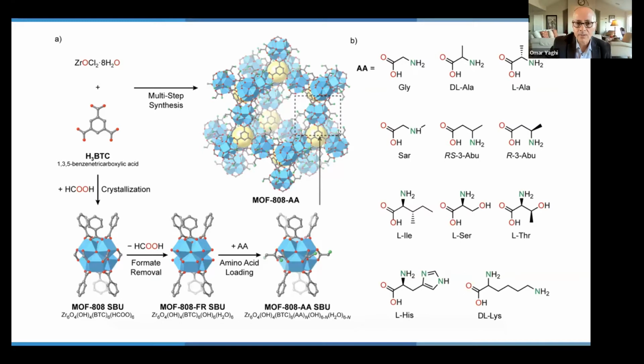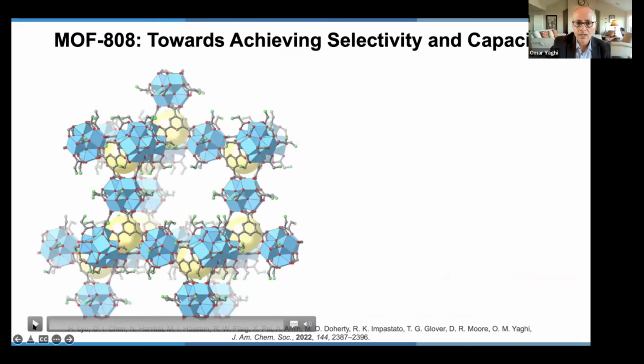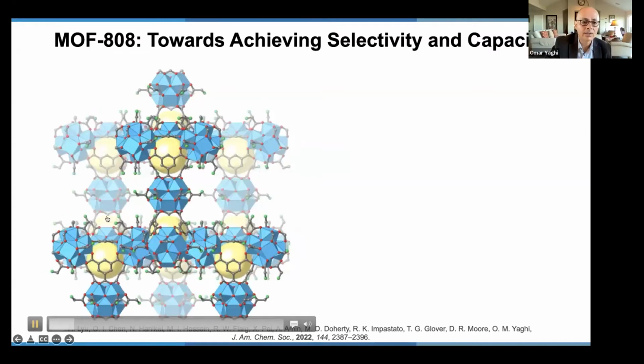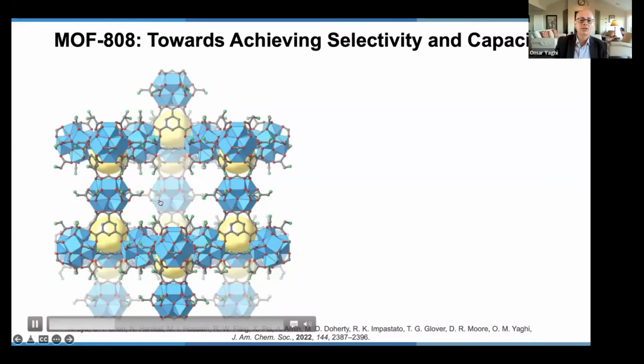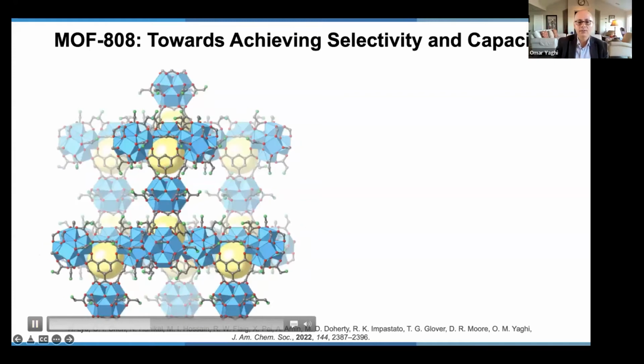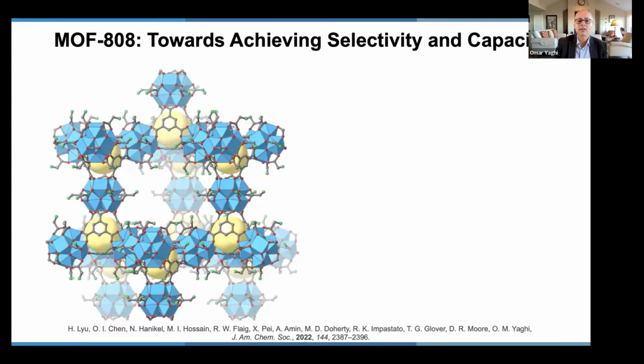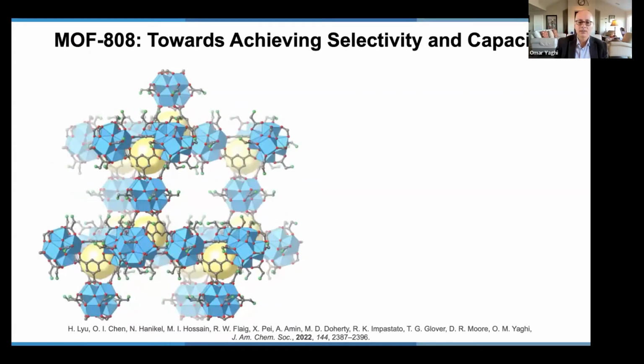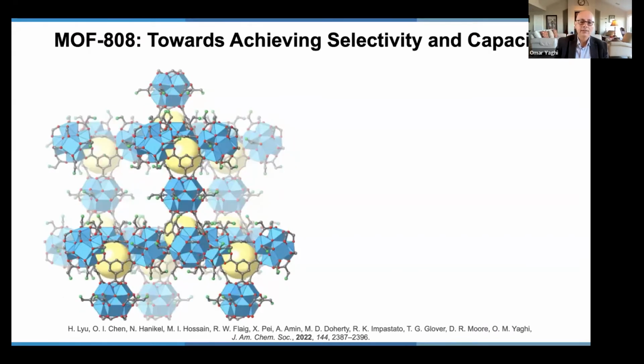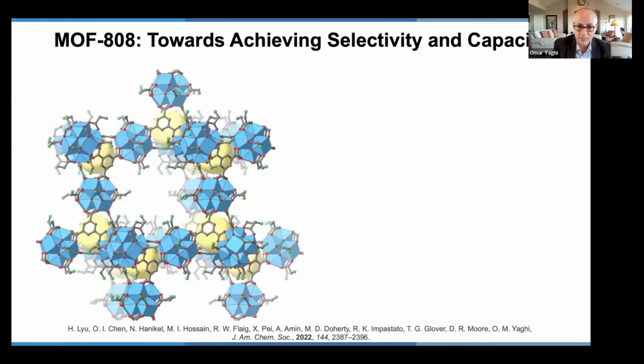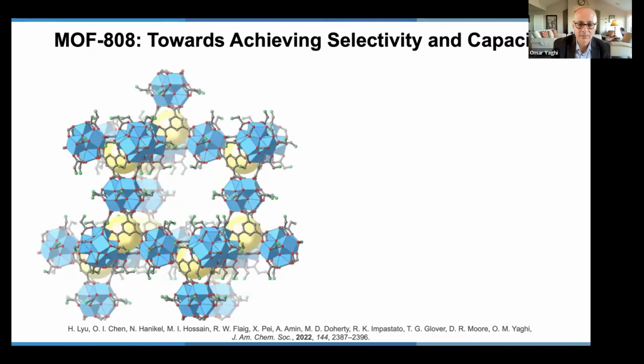This particular structure we call MOF-808. You can see these units that have the green ending is basically glycine, and you can see that the structure is replete with glycine units. Each glycine unit potentially can bind a CO2 molecule. And this is where every atom in a structure is an adsorptive site, and the structure is sufficiently open to allow CO2 in and out with great ease.